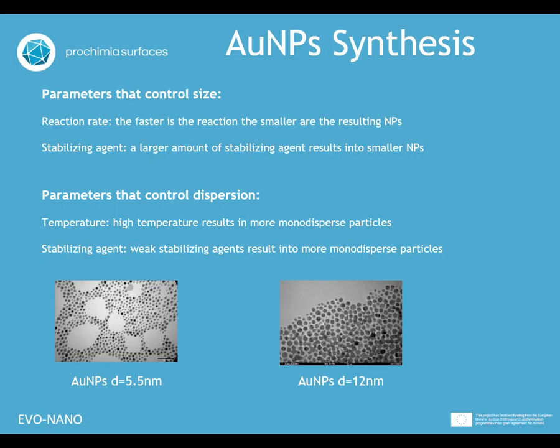Gold nanoparticles are available by different methods. Generally, they use the same reagents and conditions. So it looks like the inorganic gold salt is reduced in the presence of stabilizing agents. The most common salt used is tetrachloroauric acid, and stabilizers are carboxylates, phosphines, amines, thiols, or polymers. Reducing agents frequently used are citrate, ascorbic acid, or borohydrides.